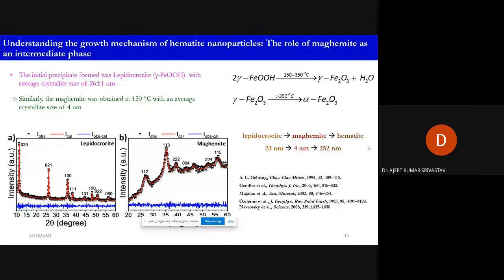And then we heated it up to 150 degrees centigrade before going for the further heat treatment. Then we found that there could be an intermediate phase, which we call maghemite, with a crystallite size of 4 nanometers. So if you see the right side, below, we have shown the XRD patterns, where it shows the lepidocrocite and maghemite phases. And then on the right side, you can see how the reaction path might go forward.